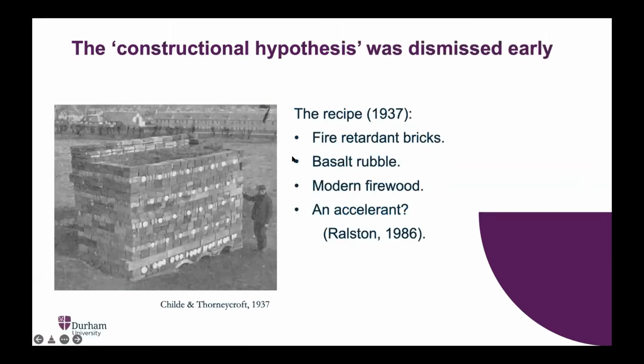The engineering hypothesis, or the constructional hypothesis, was dismissed in 1937 on the basis of an experiment where people reproduced a wall and then set fire to it for several days and looked to see afterwards what the state of the wall was. Unfortunately, they used a strange selection of materials. They used fire-resistant bricks, which obviously weren't available in the Iron Age and are the least likely material to melt. They also used basalt rubble. They used modern firewood, which burns at a lower temperature than old hardwoods. And they may have used some extra fuel, which isn't a good test of Iron Age technology.